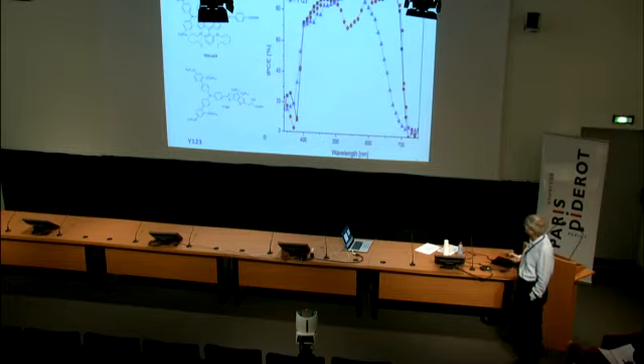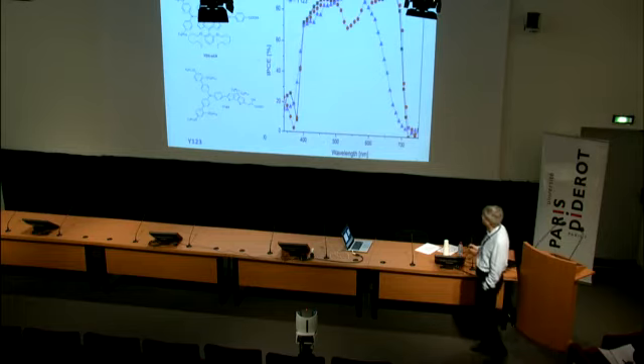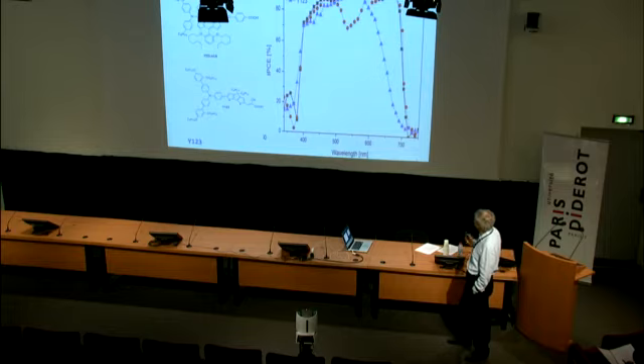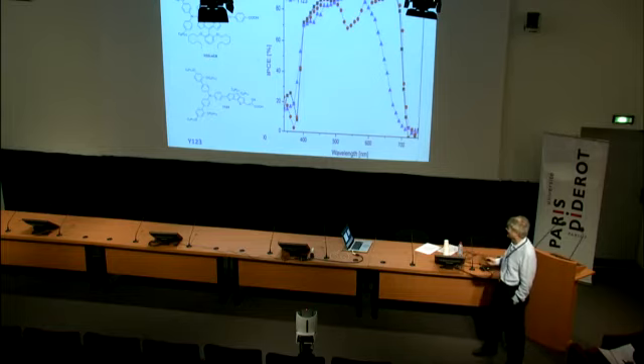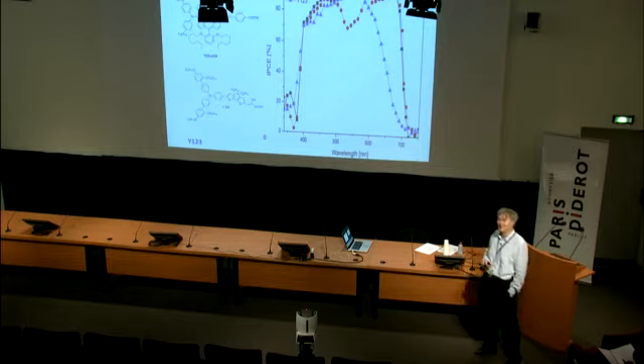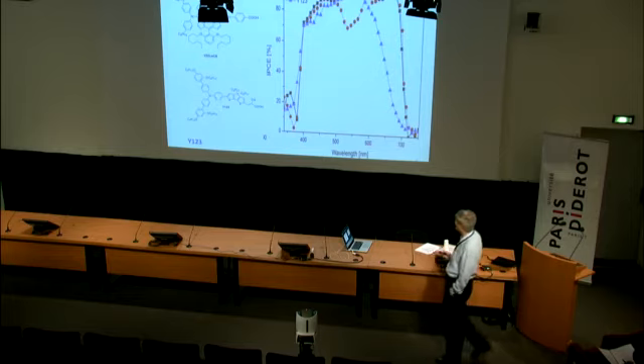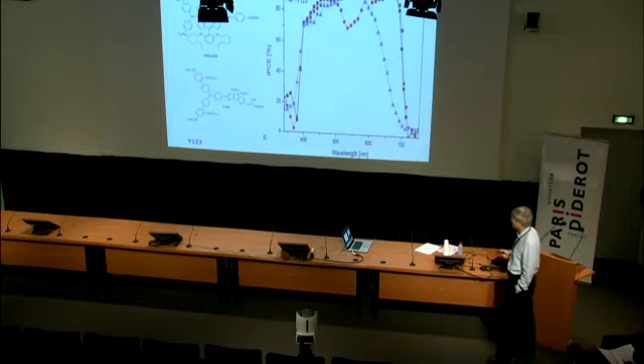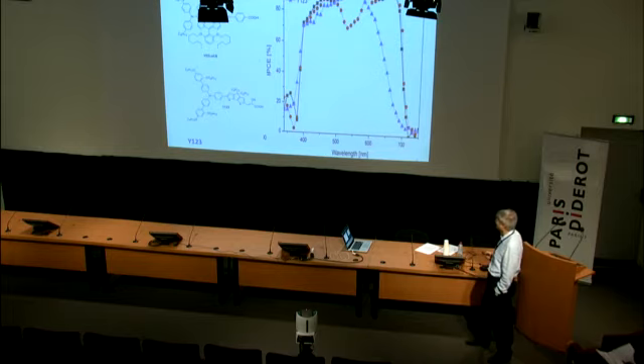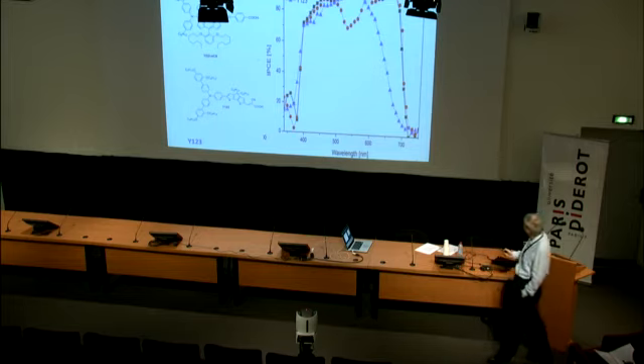And then we have to push it to the maximum. This dip here is producing a nice green color, but it's costing you photons. So we mixed in another donor-acceptor dye, which is actually the first successful dye we made in our laboratory. It's coded Y123, after Chen Yi, my Chinese postdoc, who is very, very good in synthesis. So we mix these two to get full spectral coverage. You see the black dots. We get very high conversion efficiency, over 80% across the visible until 720 nanometers.